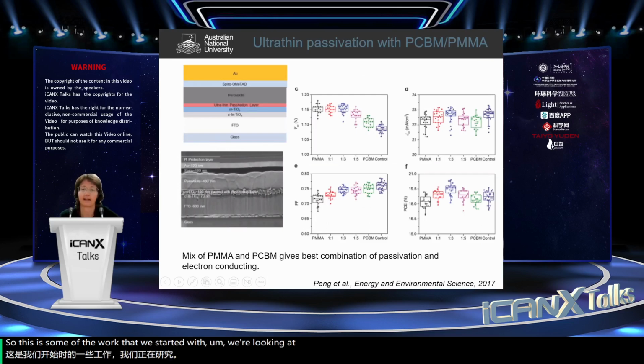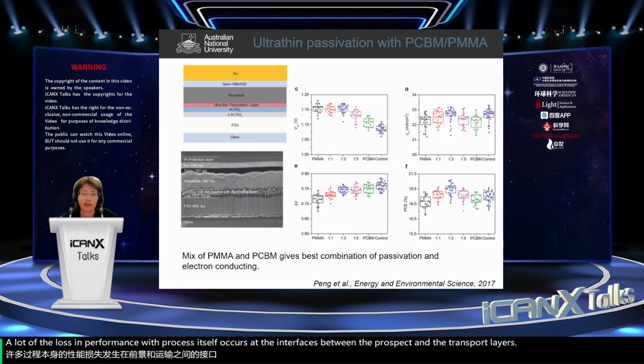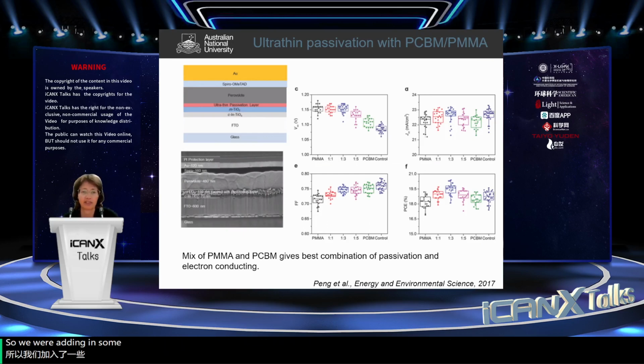We were looking at passivating the interfaces. Now, I said the perovskite itself is quite tolerant to defects, which is good. A lot of the loss in performance with perovskite cells occurs at the interfaces between the perovskite and the transport layers. So we were adding in some thin passivation layers to improve the quality of the solar cell.